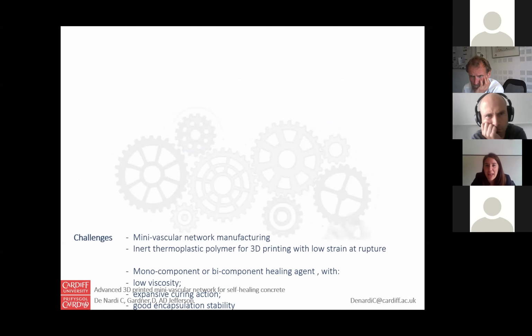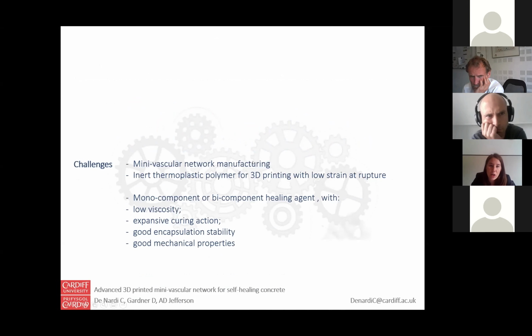So as for the challenges, and I'm asking for your help in solving some of them, we will work on manufacturing minivascular networks, because now we print them one at a time, so it's not an industrial way to produce them. We are looking for an inert thermoplastic polymer with low strain, but basically with an inert behavior. And we are looking for different healing agents, monocomponent or bicomponent, with low viscosity, perhaps with expansive curing action, with good encapsulation stability and good mechanical properties.